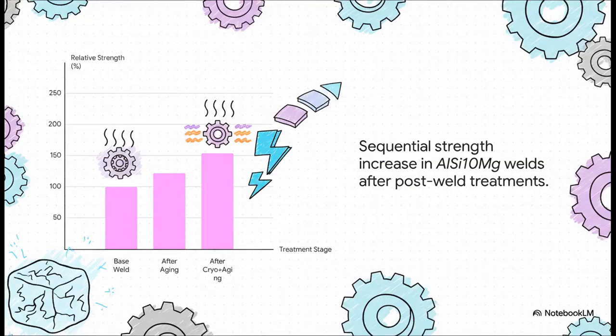And here's the payoff. Look at this. The aging treatment by itself boosted the strength by 22% over the original weld. But when they combine the deep freeze of the cryogenic treatment with the aging, wow, that pushed the total strength increase to an incredible 54%. This just proves it's not about any one treatment, but the specific sequence that unlocks the material's full potential.